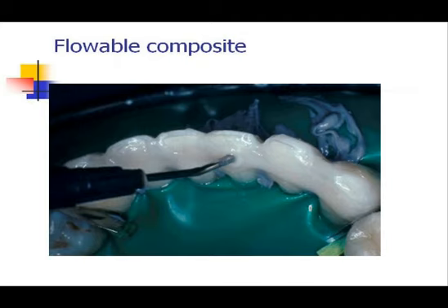I'll then go in and light cure everything for 30 seconds a tooth. Note the size of the tip of the light curing unit you're using. Make sure the tip is over the area you're curing and cure for 30 seconds. We cure for 30 seconds because we're not only curing through the composite, we're curing through the fiber. The fiber acts as a barrier for light curing at a faster rate. And so the kinetics of light curing, of polymerization, require 30 seconds a tooth to light cure.